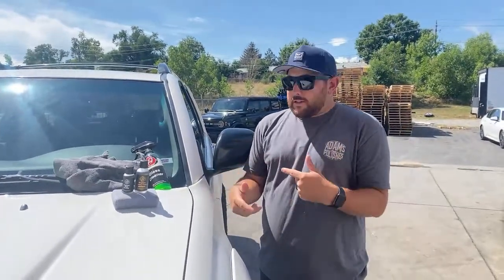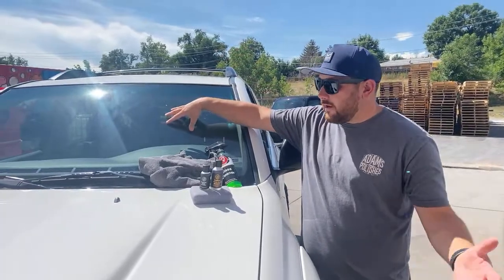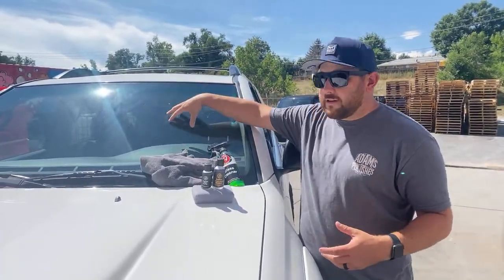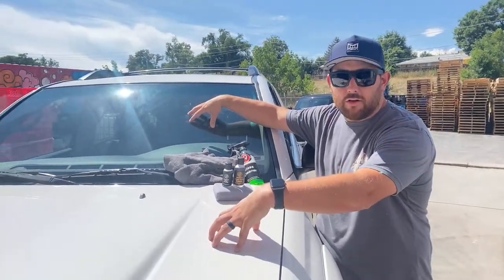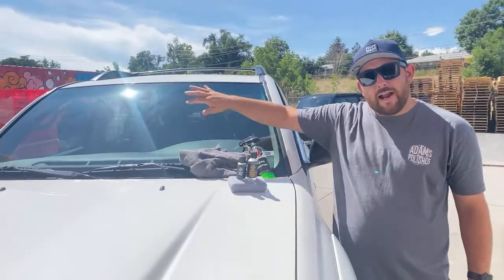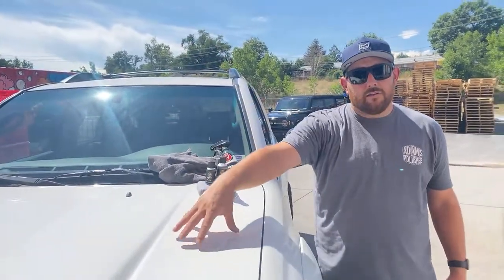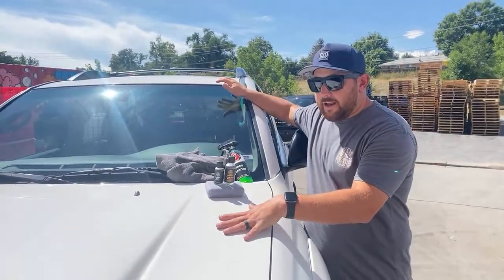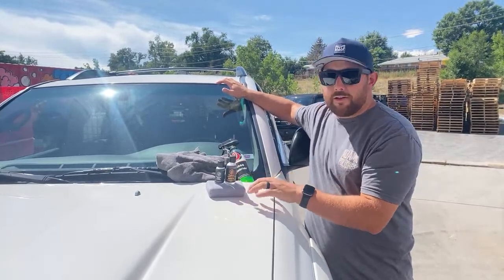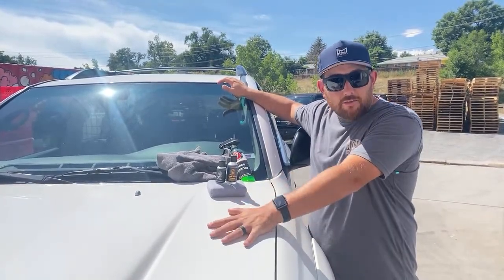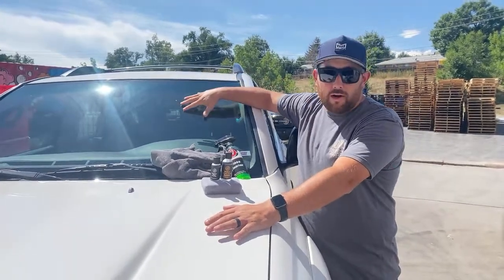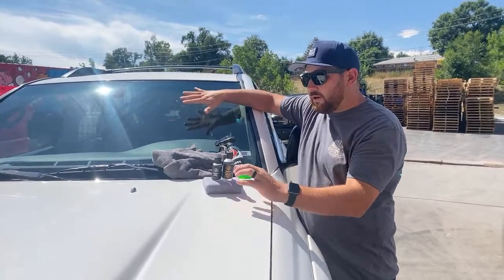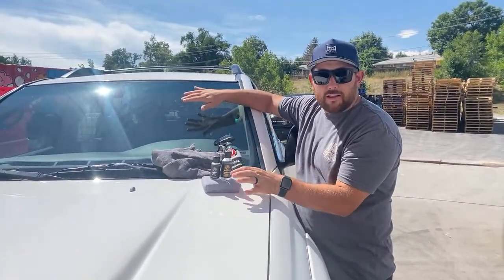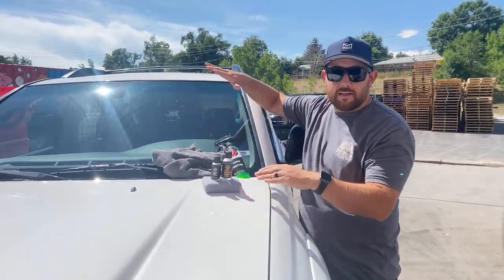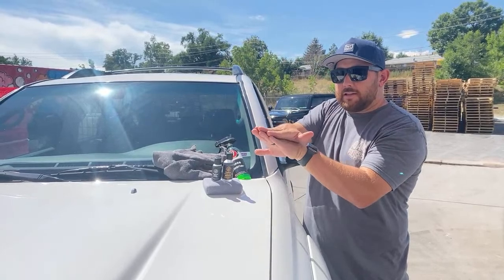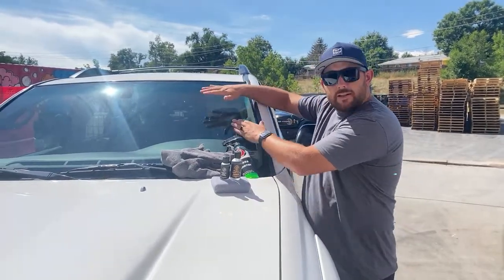Now, what we realize is glass is a lot different material or substrate than paint or clear coat. And so the graphene ceramic coating reacted a little bit different on the glass than it did on the paint, meaning paint is not overly porous. You put it on, the graphene ceramic coating adheres to it, and it stays there for an extended period of time. Glass is porous, very porous. And when you put the thick layer of polysilazane and reduced graphene oxide onto the glass, it sort of sits on top. It's like a veneer, sits on top. It's kind of the same thing with your paint, but the glass is a little bit different. It sits on the top.